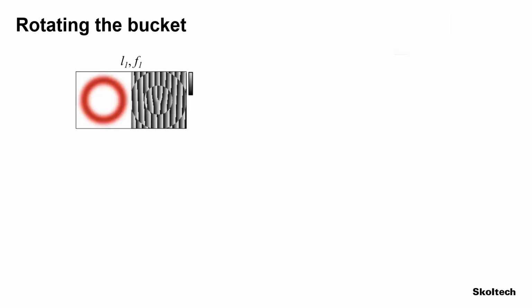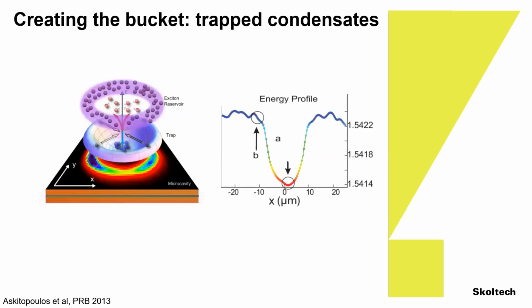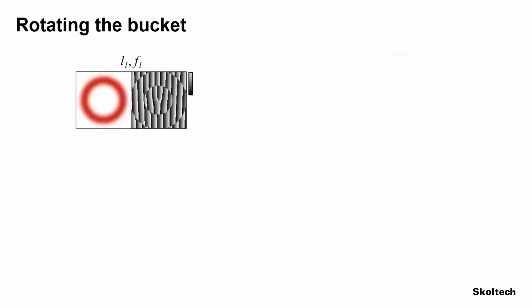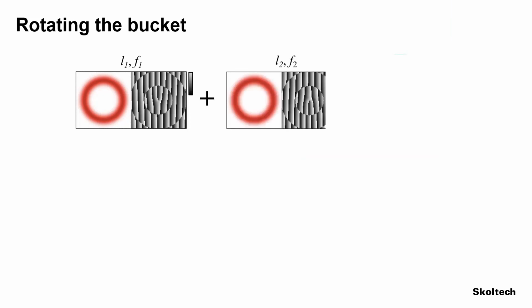So then we devised the rotating bucket experiment in the following way. We use Laguerre-Gaussian beams, optical beams that carry angular momentum. We combine two of them in a way where we can control the relative frequency of the lasers, so two different lasers, but they are locked with each other, even at different frequencies. That is very difficult. And you can play with the angular momentum of the two beams. And when you combine two Laguerre-Gaussian beams of slightly different frequency, you get a pumping profile that looks exactly like this.